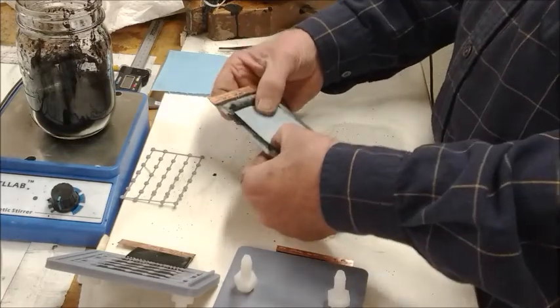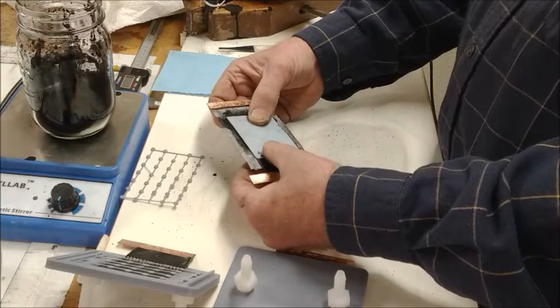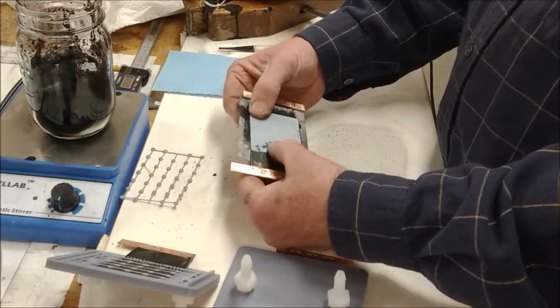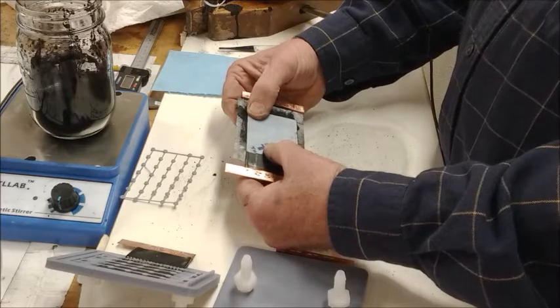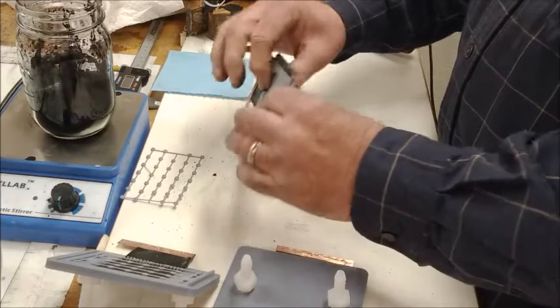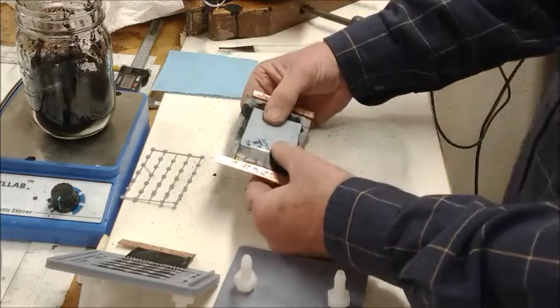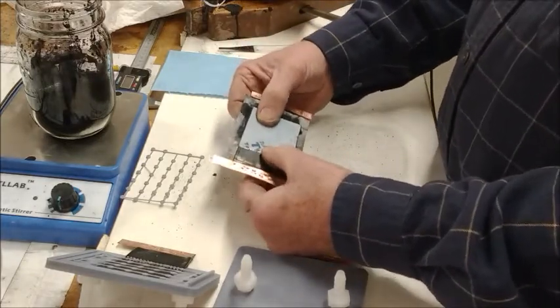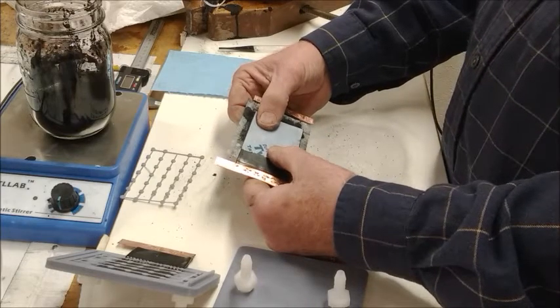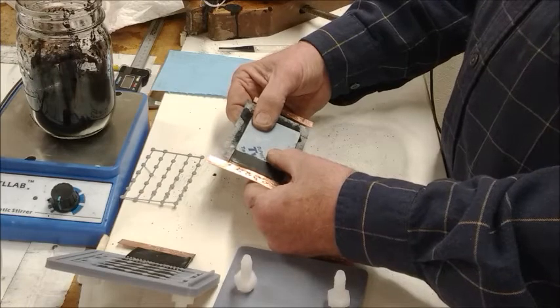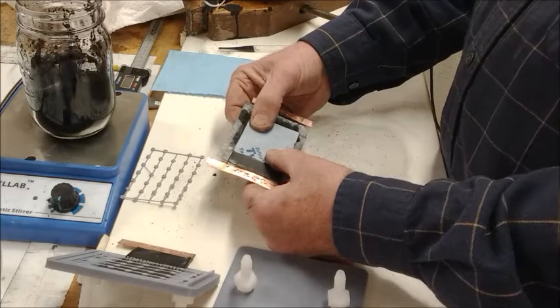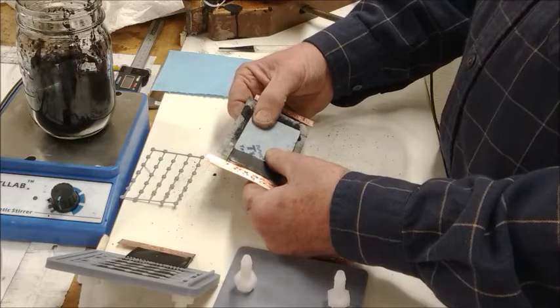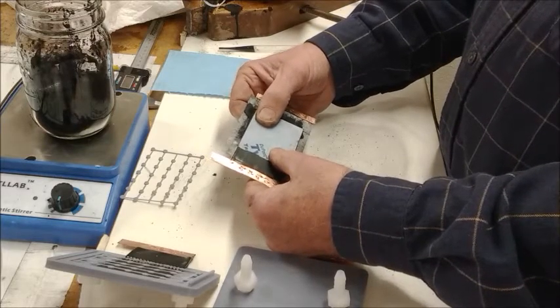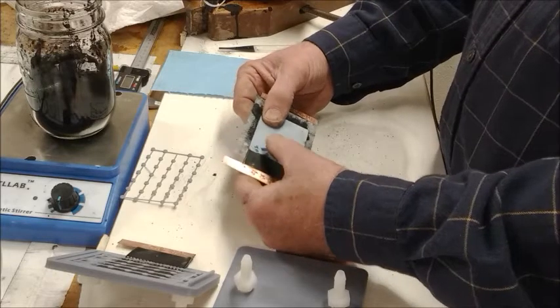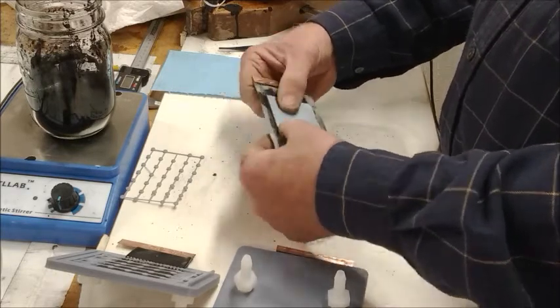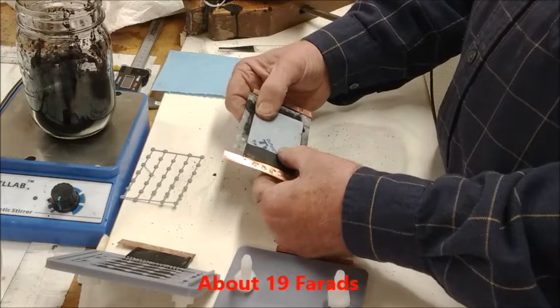Performance of this baseline cell isn't really great, but it's about 27 square centimeters in area. I don't know what the exact thickness of the material is, but when I take this sandwich, soak it in the KOH, charge it to 1.3 volts, just a little bit above the limit for an aqueous electrolyte, and discharge it through a 25 ohm resistance, I'll get performance that lasts somewhere in the 8 to 9 minute range.